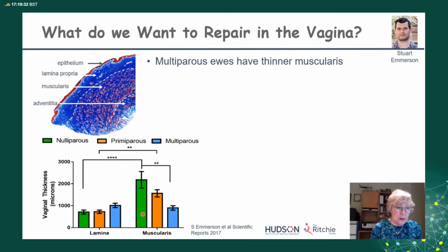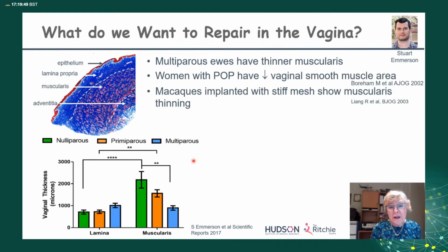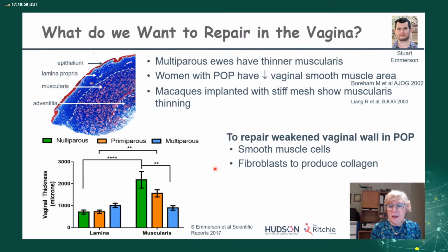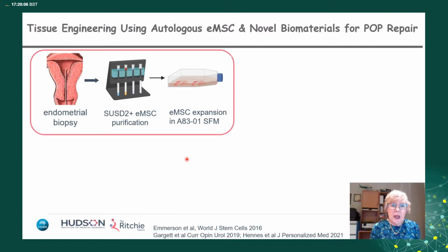Now, in order to know what to repair, we studied sheep, and we looked across the parities, and we looked at their vaginal wall structure. And the thing that we found most significantly changed was the thinning of the muscularis with increasing parity, as you can see here. Others have shown that women with POP have decreased vaginal smooth muscle area, and macaques implanted with stiff mesh show muscularis thinning. So to repair the weakened vaginal wall in POP, we really want smooth muscle cells and fibroblasts to produce the collagen.